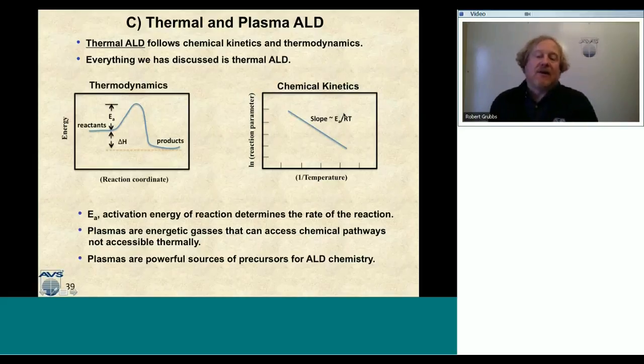And this is an Arrhenius plot, which is the natural log of some reaction parameter that monitors the progress of the product formation as a function of 1 over temperature. And the slope of this line is proportional to the activation energy of this barrier. Now, this is all thermodynamics, and this is all chemical kinetics.